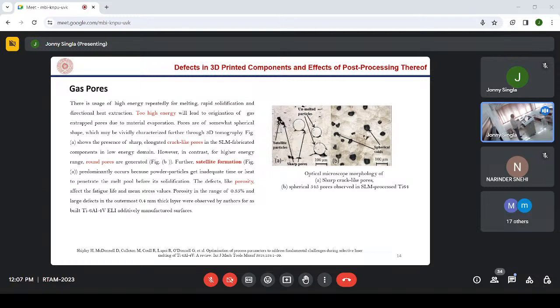Sometimes these gas pores appear like crack-like pores, and sometimes we have round pores. For higher energy range, we have round pores. For lower energy range, we have crack-like gas pores, right? So whenever there is a gas pore, that means it is porosity. You are introducing porosity, right? So that is basically not desirable.